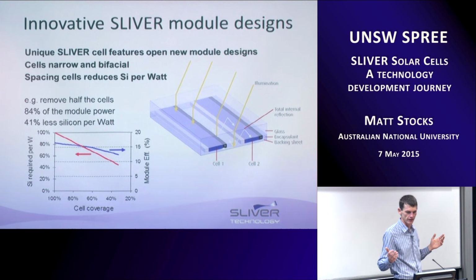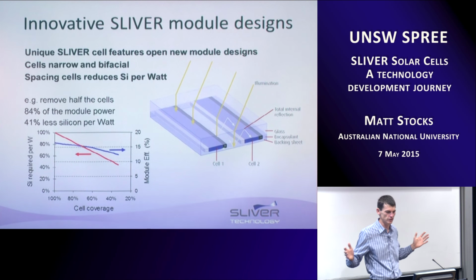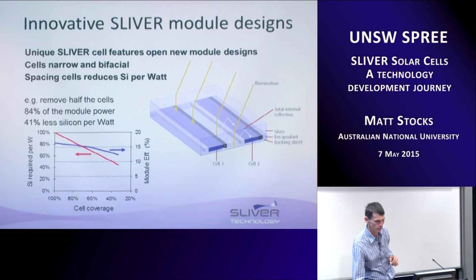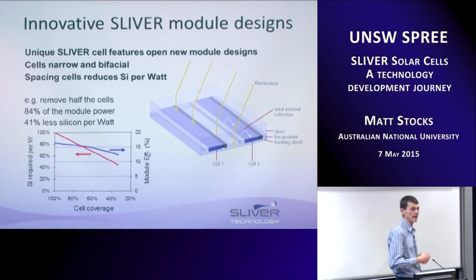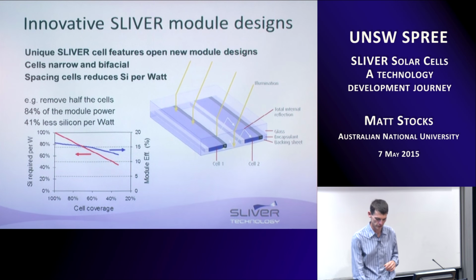By spreading the cells out, so the red curve there is imagining spreading the cells out and reducing the amount of silicon. So as we spread the cells further and further apart, what we're getting is silicon saving, but the efficiency drops off much more slowly. So in terms of grams per watt, again, it's most beneficial to spread the cells out, is the best economics.